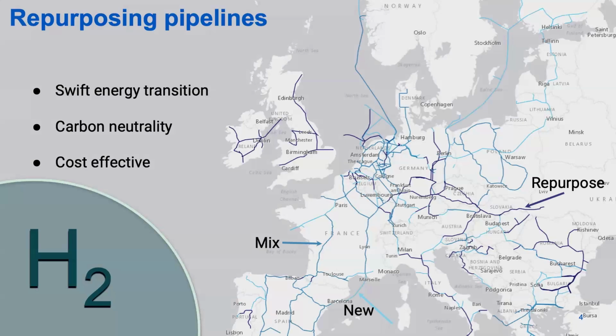An extensive pipeline network already exists in Europe. Repurposing or reusing these pipelines for hydrogen service makes sense for a speedy energy transition to achieve carbon neutral goals. This measure is not only cost effective, but economical. However, directly swapping the natural gas with hydrogen gas is challenging because now we all know how hydrogen can impact the material properties of these pipeline steels. In addition, factors such as the age of the pipelines, the in-service degradation due to the natural gas transport, and the manufacturing technology all have significant impact on how hydrogen interacts with these steel materials.